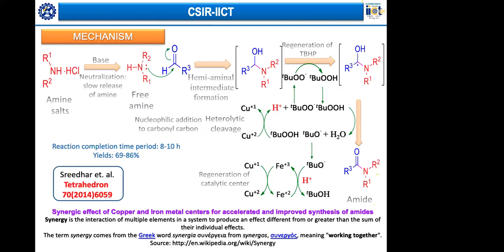Then our interest is to understand how and where exactly these metal ions are acting as catalysts. If you see here, copper 2+ is getting converted to copper 1+ at this stage, and this has to be regenerated into its normal copper 2+ form, and that is happening at the later stage because of the iron present in the Fe2+ and Fe3+ form. These are the two key things in this mechanism. The rest is all known, but what is interesting here is copper 2+ getting converted to copper 1+ in situ, and this copper 1+ has to regenerate back to copper 2+, and that is happening because of the presence of iron 2+, which is playing the major role in the catalytic activity. So this synergetic effect of copper and iron in this example was what gave improved synthetic yields for the desired materials.